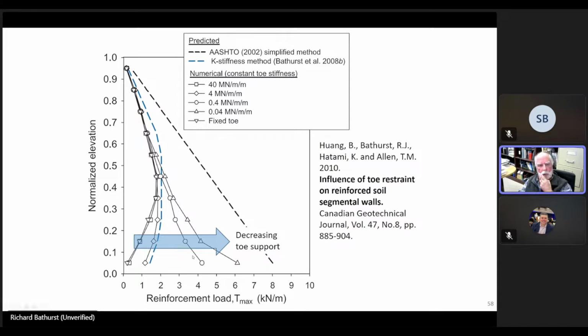The symbols represent different reinforcement layers, and the location of the reinforcement layer has been normalized with height of the wall. So this is the top of the wall, and then we go down to the bottom of the wall, and we can predict what the load in the reinforcement is at any stage during the test. So using a calibrated FLAC model, we then reduced the toe support numerically. And what you can see here is as the toe support decreases, the load in the reinforcement goes up.